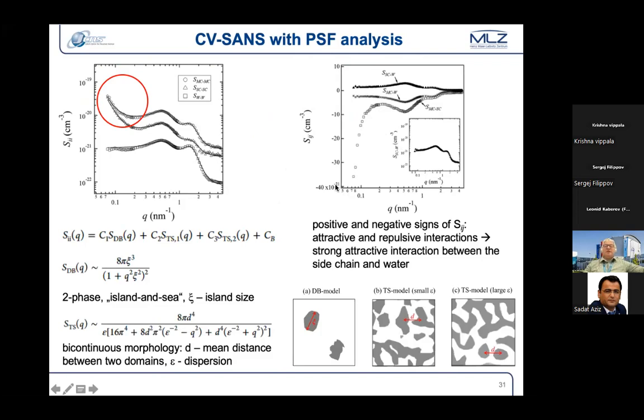So now these are the self-terms of Nafion. These are the intermediate terms. The self-terms show some scattering features. It is a sort of bicontinuous feature which has been interpreted using the Teubner-Strey model, and the Beaucage model was used for low Q. We succeeded in characterizing all these 3 scattering self-terms, and the cross terms show a negative sign for the main chain.